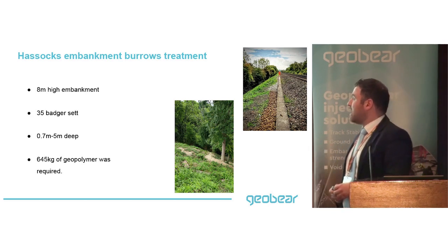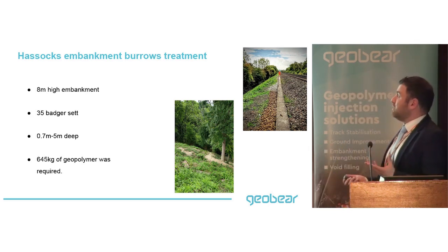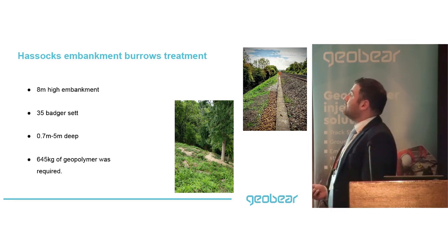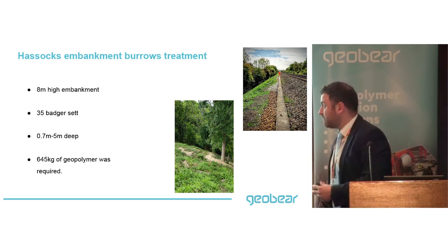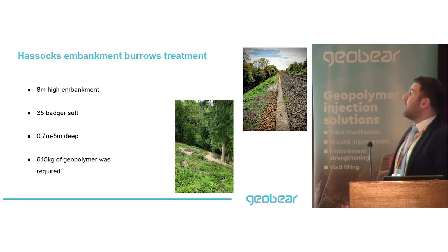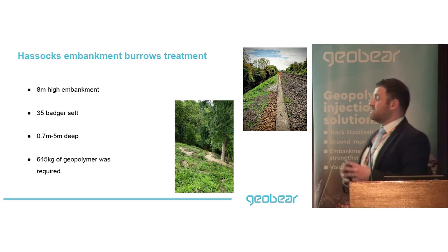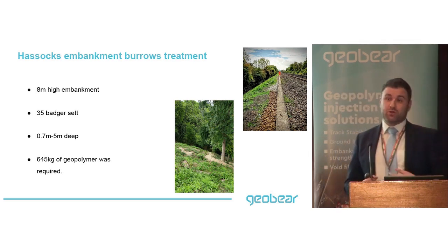This example is from Essex, where there was an 8-meter high embankment with 35 badger sets, with depths ranging from 0.7 to 5 meters deep, so some of them quite deep. I've seen similar things on other railways, and we were required to install 645 kilos of geopolymer to fill those 35 sets.